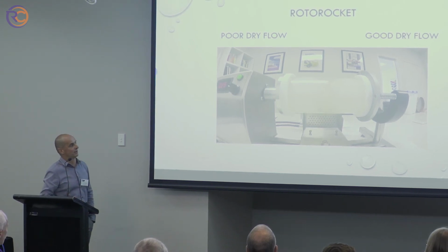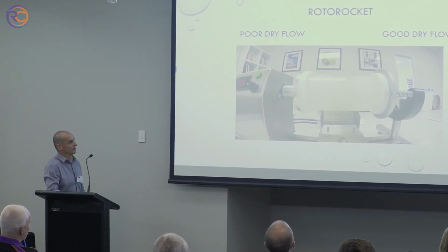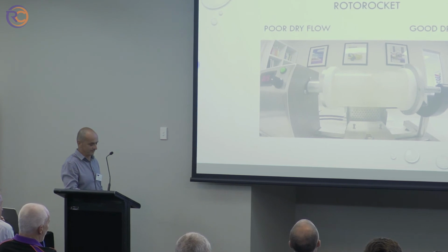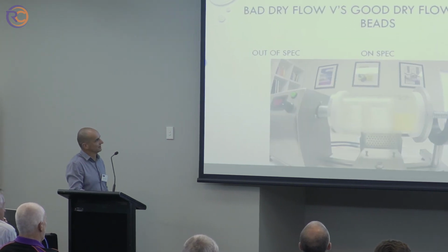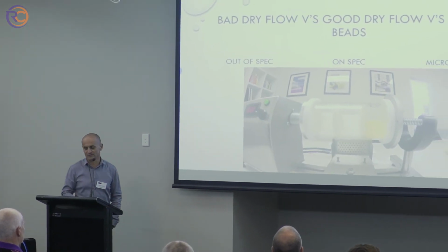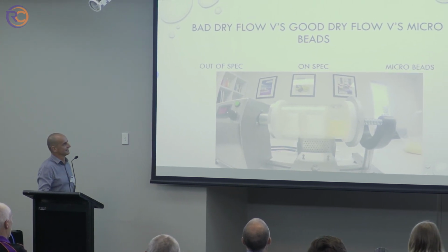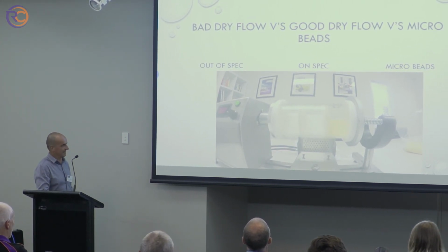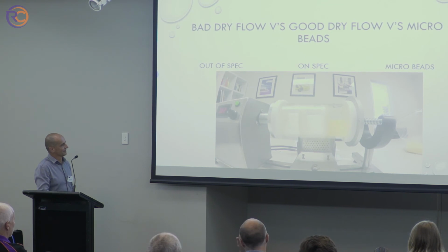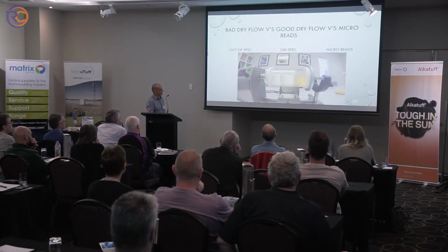And now the powder is all solid and it's cooled down. So what we did also is we just thought we'd throw in some micro beads, and again you can see here the poorly ground powder, good powder, micro beads, all the same weight. Micro pellets take up a lot less volume. Just to show you the flow, again the micro beads flow very well.